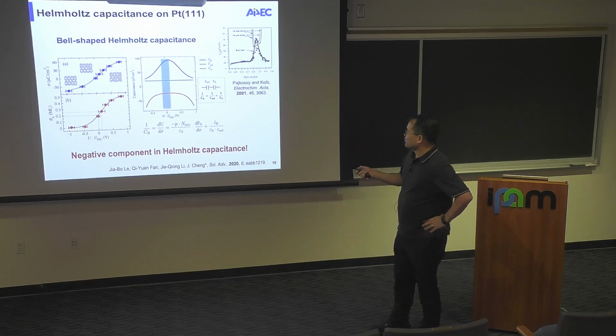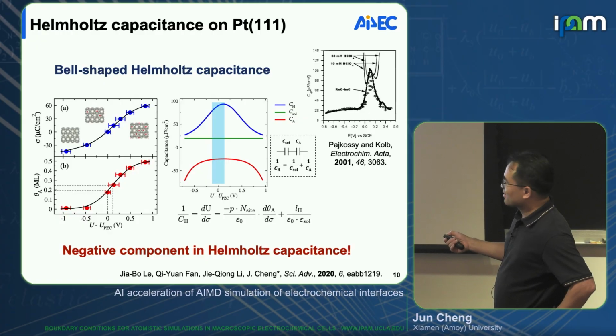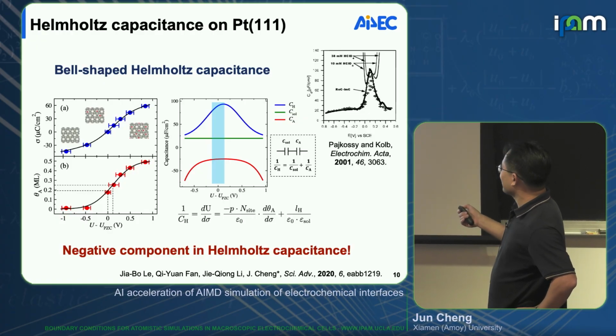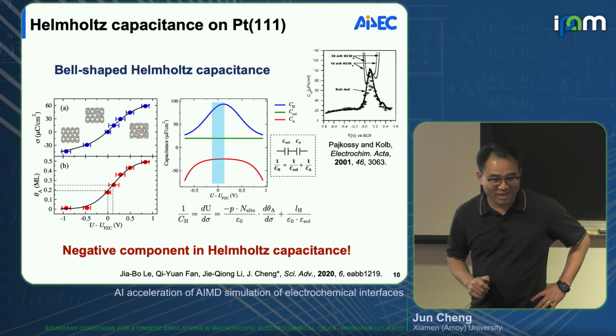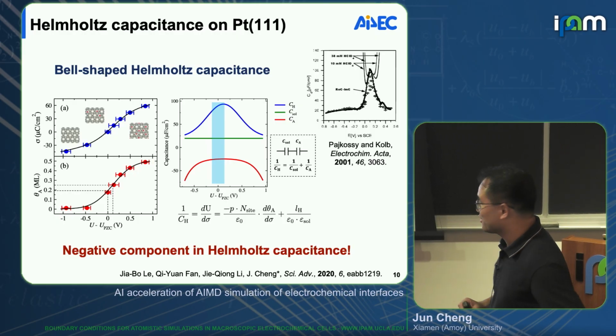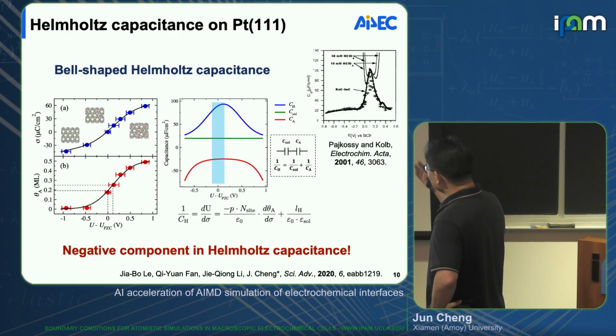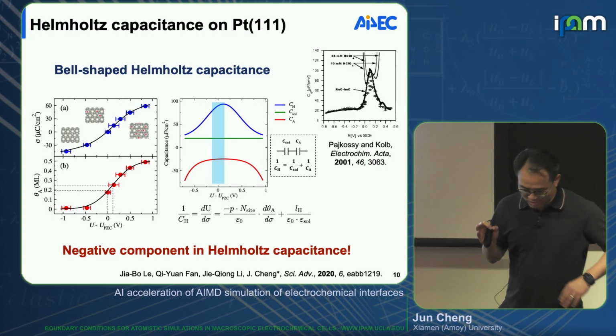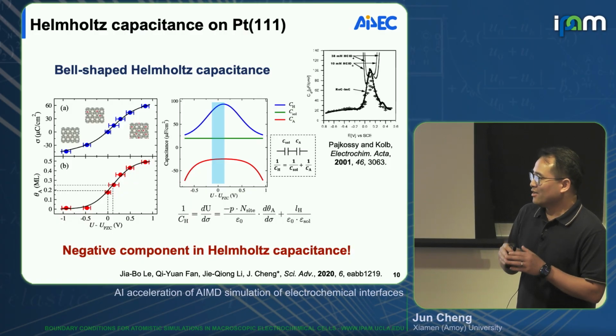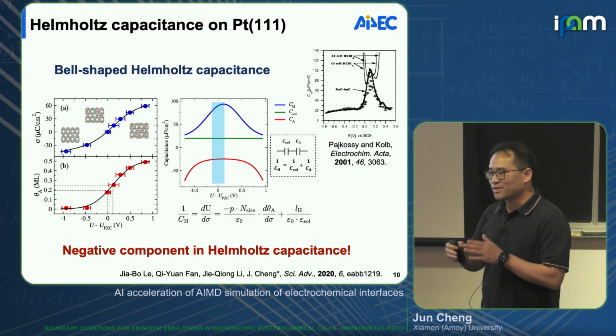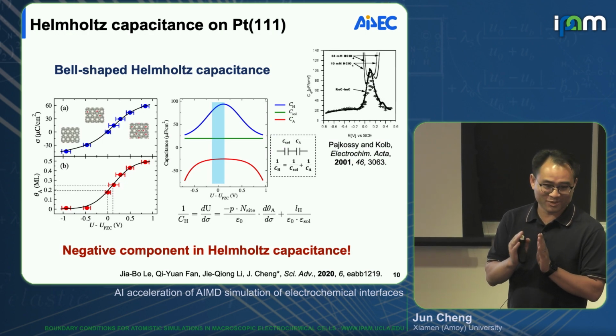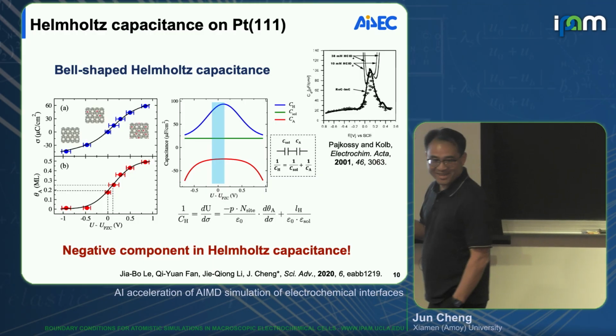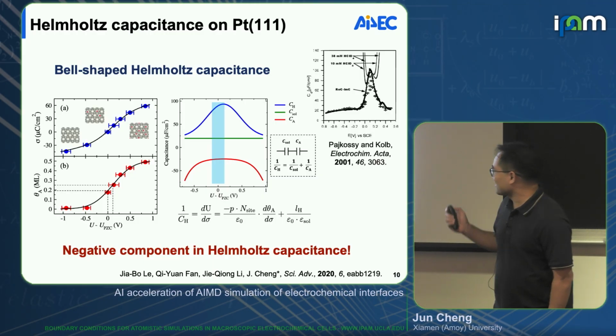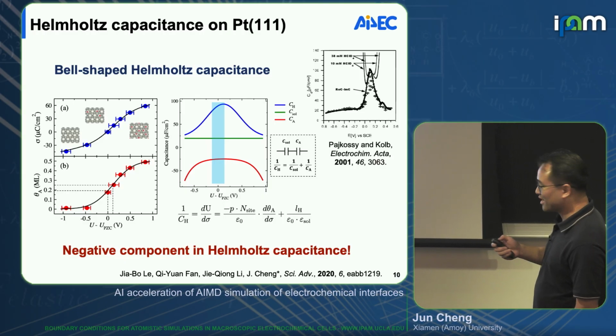So that's exactly the reason our differential capacitance curve looks much broader than the experiment. Because experimentally, at this potential you have hydrogen UPD, right? And the surface is covered by hydrogen. Okay, so that's another discussion. Right now we're looking into the double layer region, but of course for the real platinum case, the double layer region is too narrow to be compared against, right? Anyway, the pH effect certainly should be taken into account.